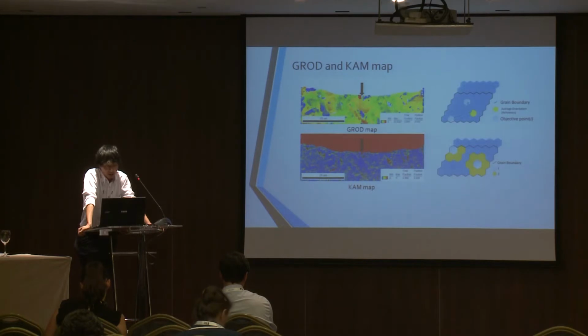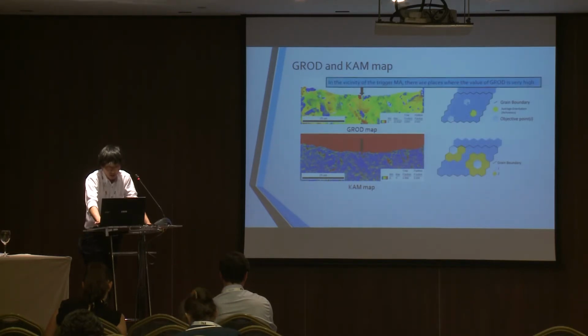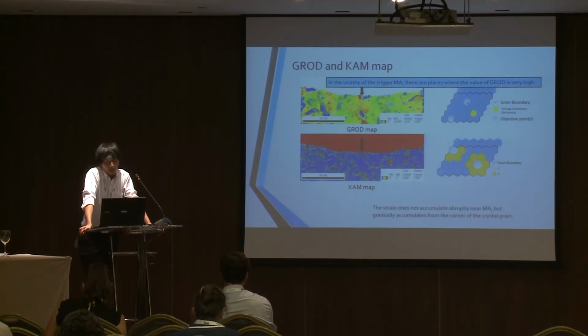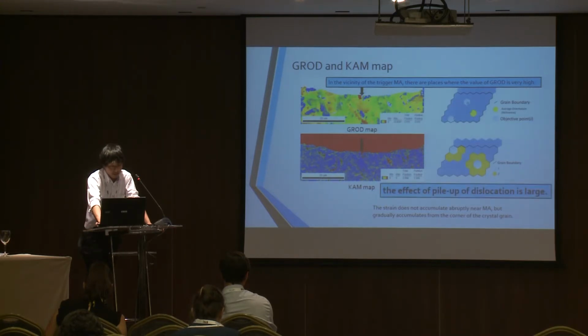On the other hand, the KAM map shows the orientation difference from the neighboring parts, and according to this, the left part of the MA is not displayed in red. So, the strain doesn't accumulate abruptly near the MA, but gradually accumulates from the corner of the crystal grain. In any case, the effect of pile-up of dislocations is large.